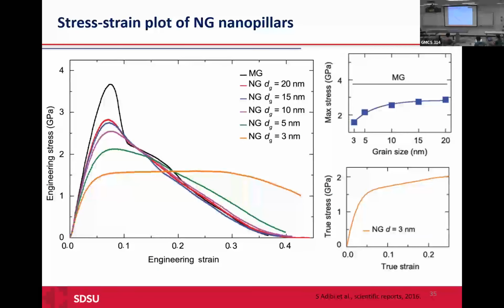Okay, these are the results that we got from the stress strain curve. You can see that this is a metallic glass sample, and those are the results with the nanoglass with different grain sizes. The metallic glass sample, as you can see, shows a very sudden failure, which is the indication of shear band formation in the material. But as you go to the nanoglass material, this shear band formation is decreased, and also at some point you can see some serrations in the material.